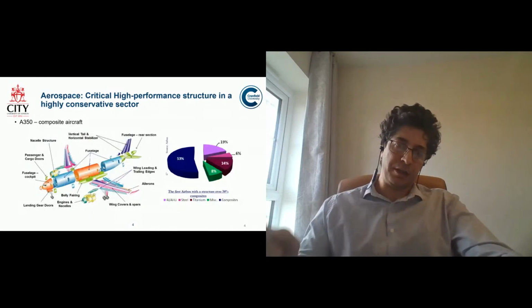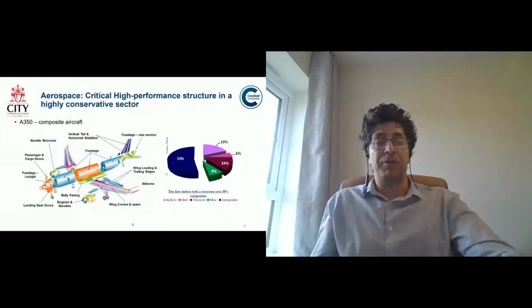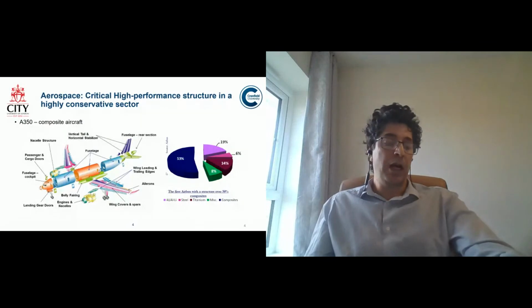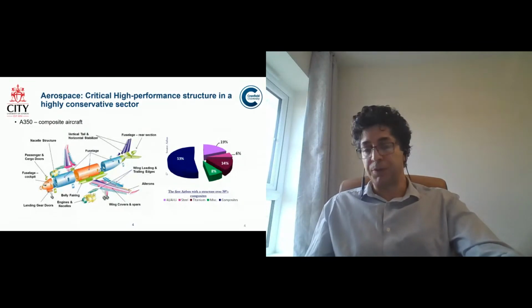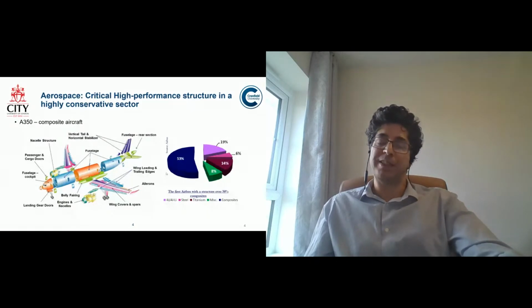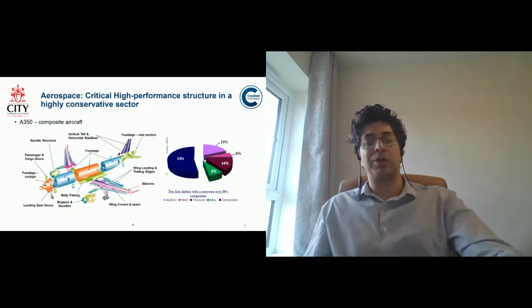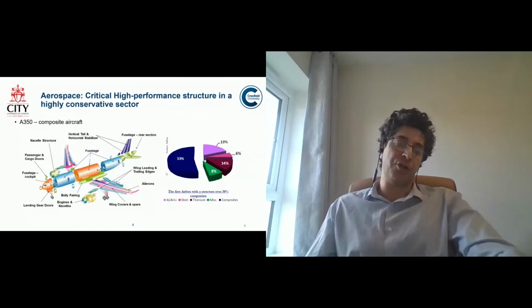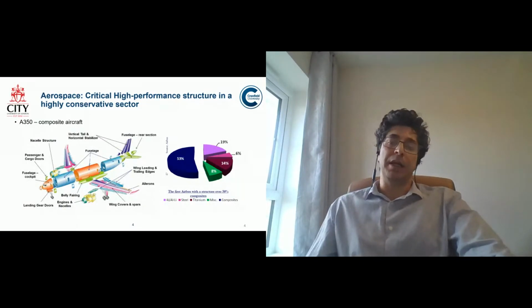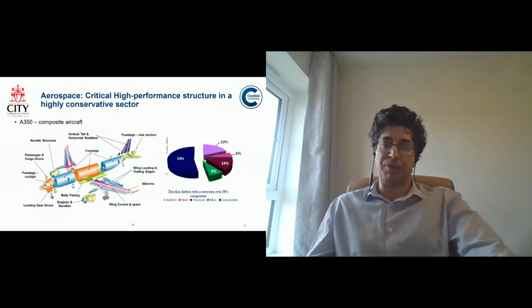So it's a very highly conservative sector. And we talk about using, for example, carbon fiber composites at a volume fraction of more than 60%. Carbon fibers, each 6 to 10 to 15 microns in diameter, in the primary structure of the aircraft. I'm talking about the wing structure and the fuselage structure, where the majority of the load is going to be taken up. That's where, if there is any damage, there may be a catastrophic failure,